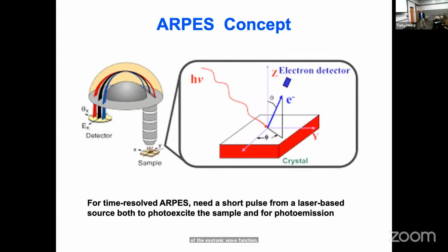Well, just to remind you, in the usual photoemission, angle-resolved photoemission setup, you have some incoming photon that has an energy appreciably above the work function. It ejects an electron, then you detect the energy and angle of the electron, so you get the full momentum of the electron. Then you work your way backwards and you can figure out the energy and momentum that the electron had while it was still in the solid. And in the case of 2 dimensions, it's really very nice and straightforward. You don't have to worry about any projections. It directly translates the momentum in the plane into the momentum in space, and you also know the energy of the electron.